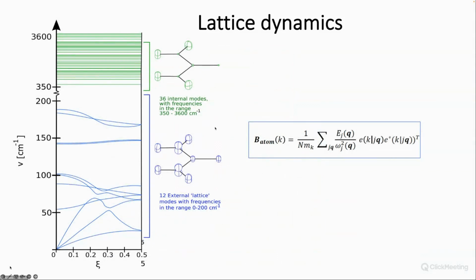Okay, so here's a plot where I have summed up all these phonon modes for urea, and you can see that the mean square displacements are fairly small for the heavier atoms for the internal modes, and they give a fairly large contribution to the hydrogen atoms. And the same if we go down here, we can see for the low frequency modes, the lattice modes of vibration, collective molecular motions, there we have lower frequencies, and therefore we also have higher displacement parameters.